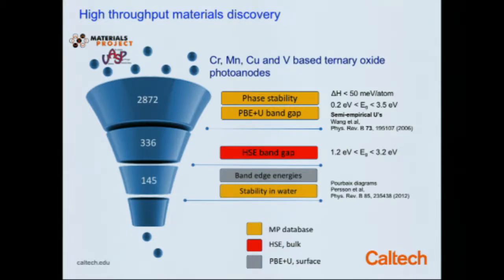From the electronic structure, we were able to derive effectively the Pourbaix diagrams that indicate the electrochemical stability at a given pH.